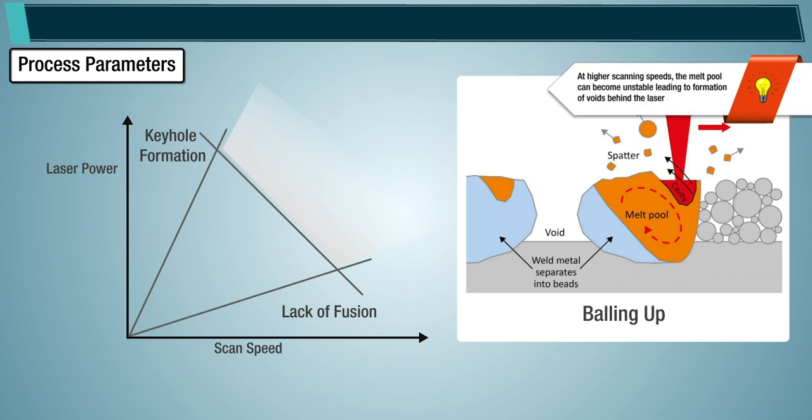Note: at higher scanning speeds, the melt pool can become unstable, leading to formation of voids behind the laser, causing the melt pool to break apart into separate islands that solidify as weld beads.